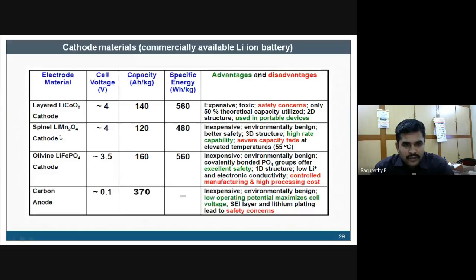Lithium cobalt oxide, spinel, olivine-based compounds. Look, each material has its own advantage and disadvantage. In the case of lithium cobalt oxide, look at this, the energy density is higher and the specific capacity is also 140. But it's very expensive, cobalt and other things. That is the reason why we can't always think of this material. More than that, it's only possible to take 50% of the lithium, which means only 0.5 of lithium is reversibly possible.